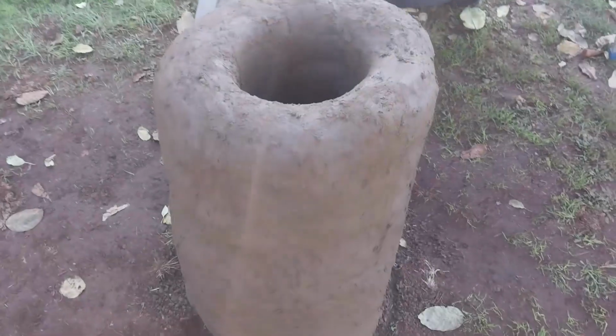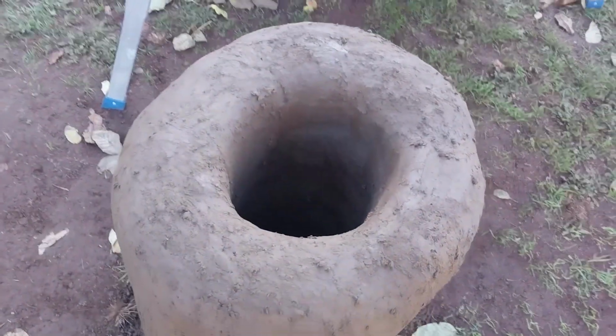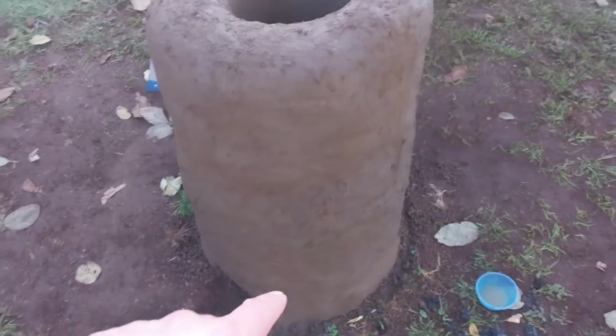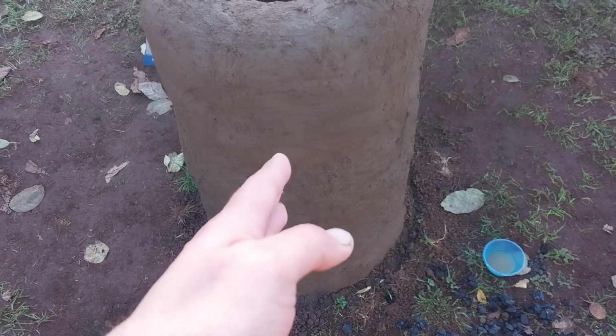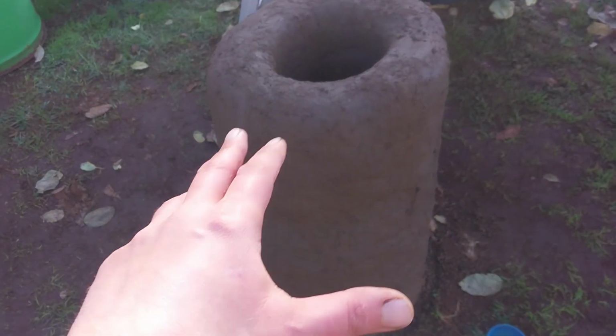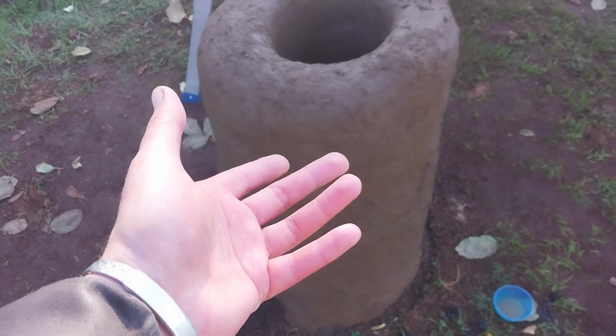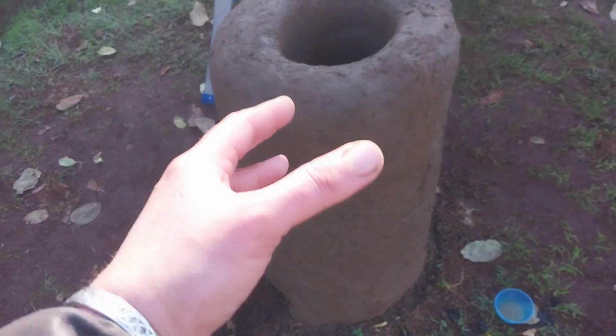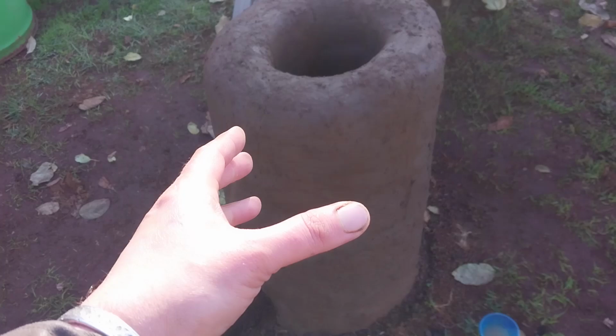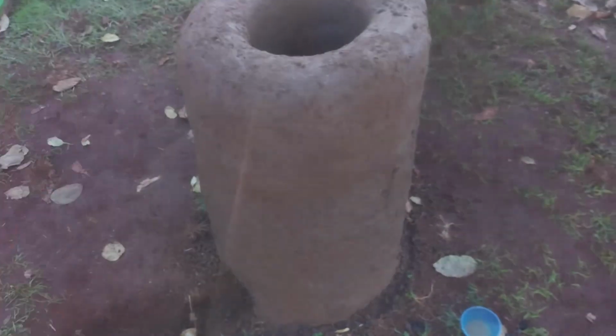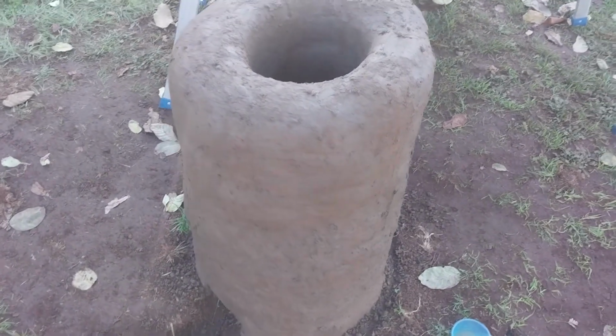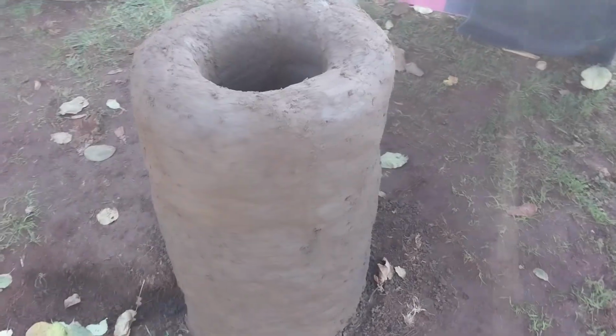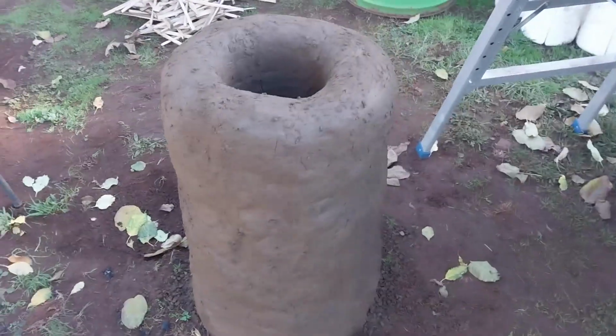So this isn't just a band-aid fix where we've just put fresh clay on the top. No, we've actually fully cleaned out the bottom of those cracks, squared it off, and then worked clay all the way back down in there. Now this had fully settled, which means there shouldn't be too much more movement left in this, although that will change due to humidity and such, especially with the humidity and temperature shifts that are going to be coming for me with the coming rain. But this will drastically minimize the amount of future cracking that we're likely to see.